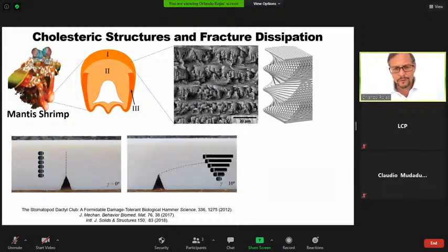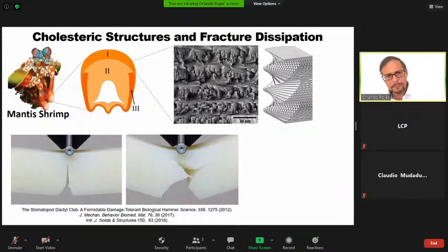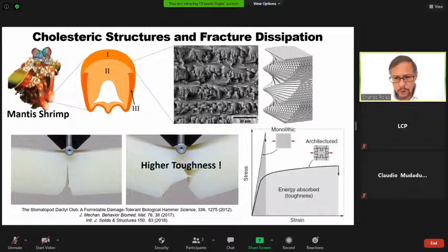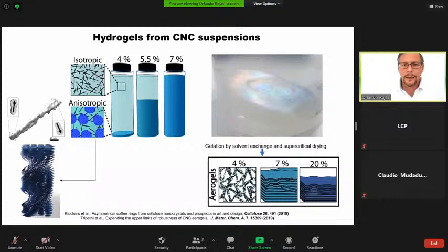And for that reason, having this type of situation, the crack propagation is quite tortuous, and that means that we have very high impact resistance. So imagine on the left, bottom left, and then in the center, how the helicoidal structure of the material makes the breaking point such that the stress propagation in the left is linear, more or less, but on the right is more tortuous, and that makes the material super strong. So using this concept, something that we attempted to do was to achieve similar performance with cellulose nanocrystals. So the work that I show next briefly was published last year, using hydrogels from nanocrystalline cellulose, CNC, that were suspended. And when we suspend the nanocrystalline cellulose in water, we have this chiral nematic assembly that I have explained earlier in the anisotropic bottom phase.